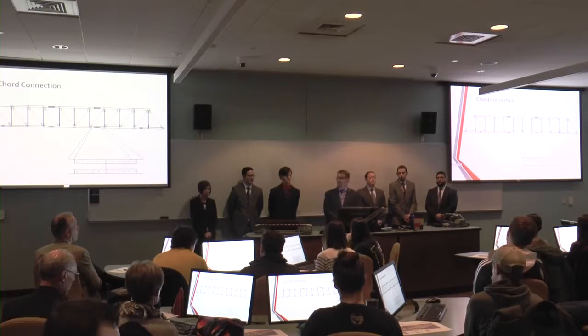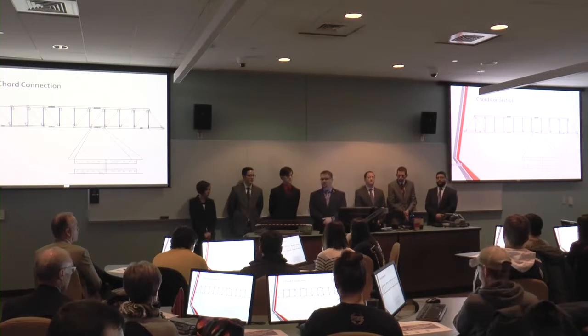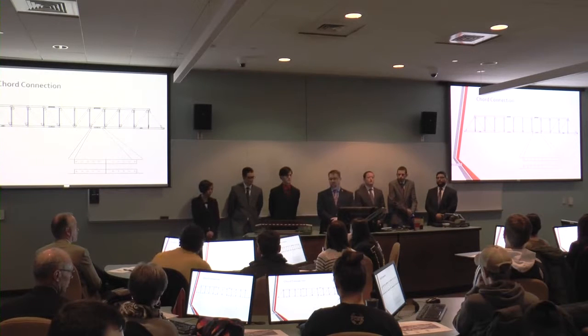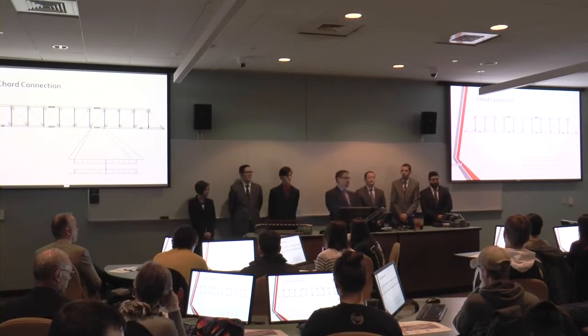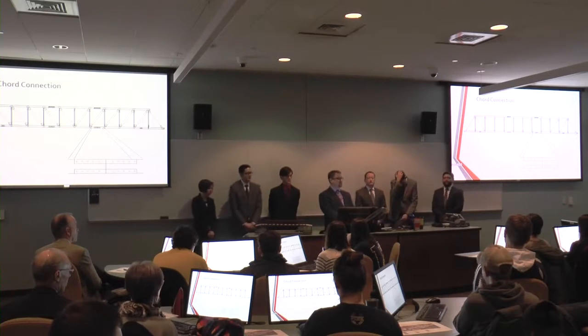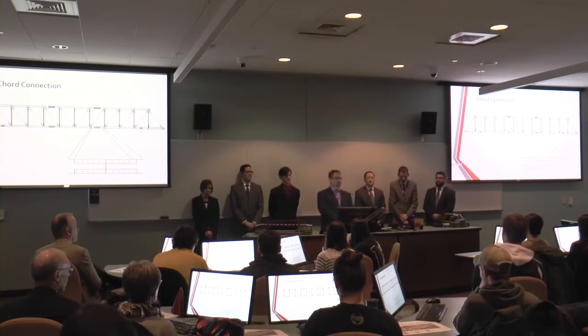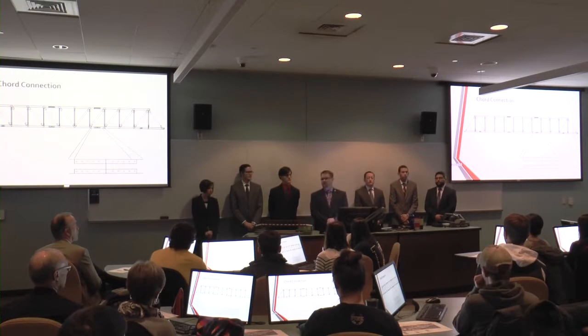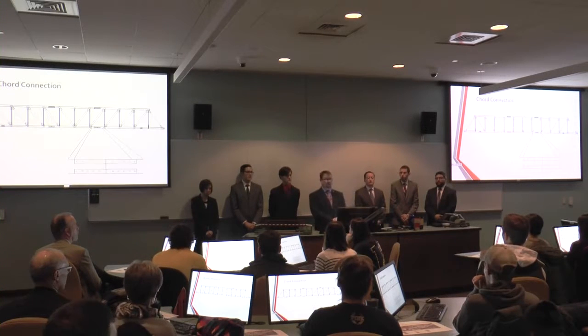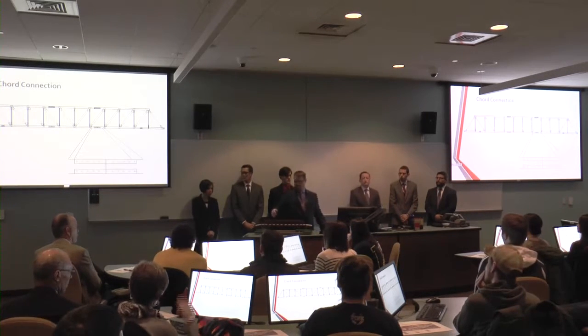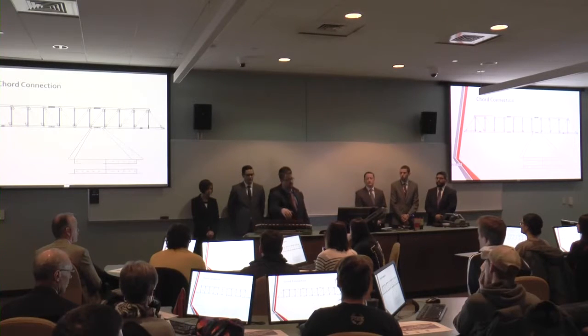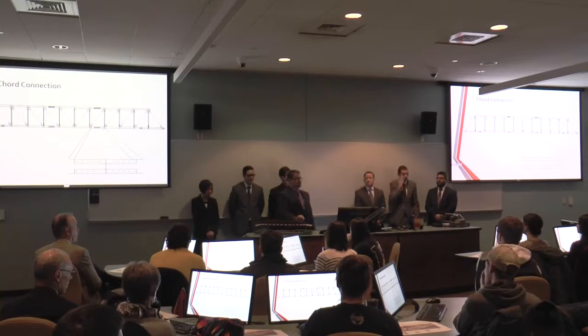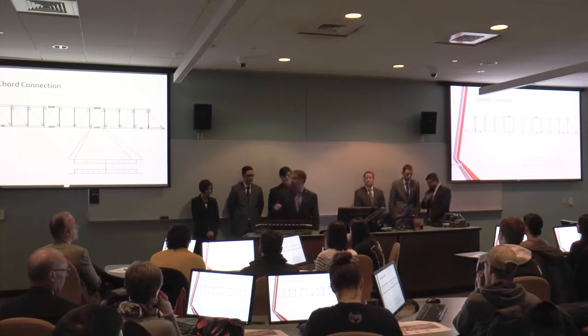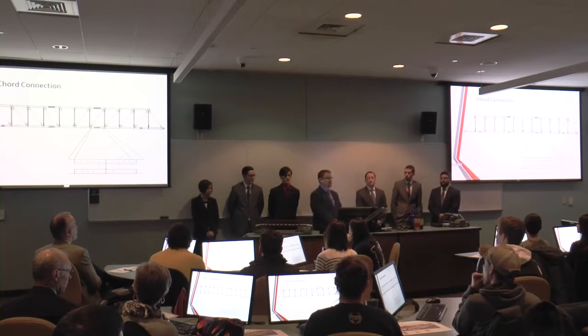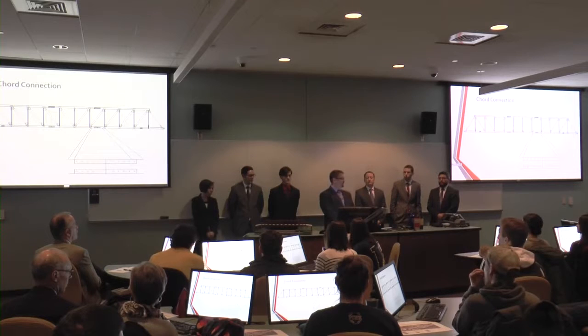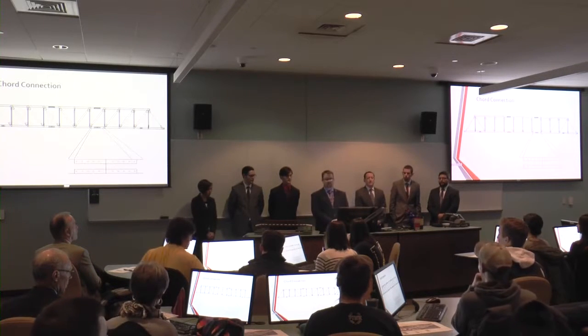So the reason why this is a major concern goes back to the expansion and contraction that I was talking about earlier. If you put 2 rows of bolts and then you put a gusset plate on the outside and you restrict the ability for the wood to expand and contract, it will then cause cracking that is parallel to the grains. So our fix to that, as you can see, is instead of making our lower and upper chords at the nodes, we chose to make longer sections, and we would connect in the middle of the bays at 6 different connections. And at this point, when we were not connecting at the nodes, we were then able to connect the diagonals and the horizontals.